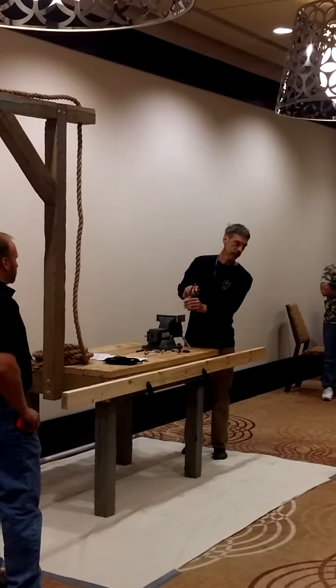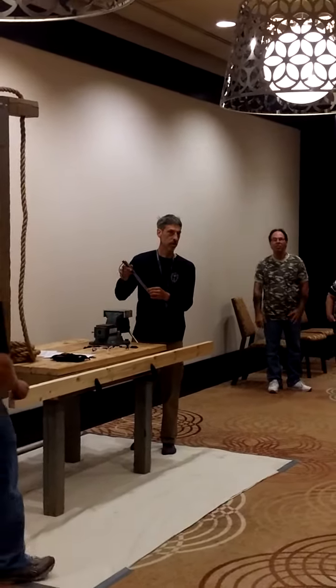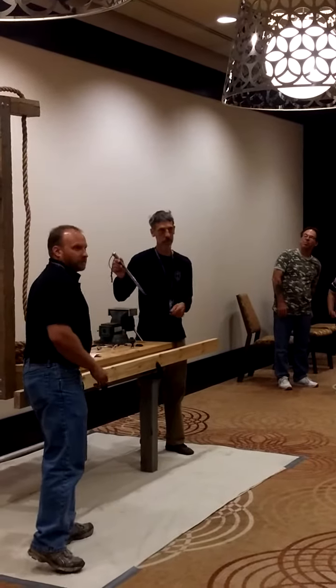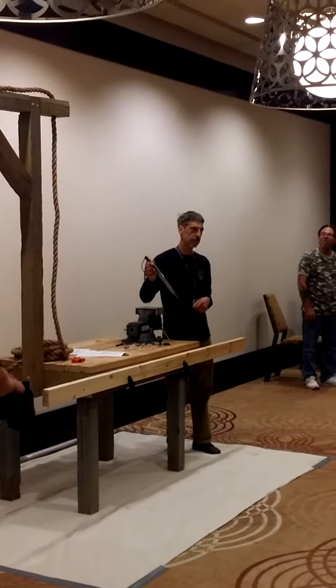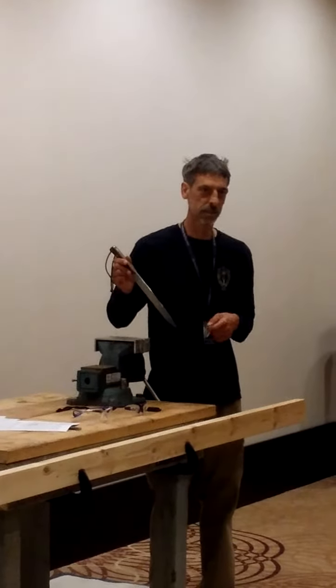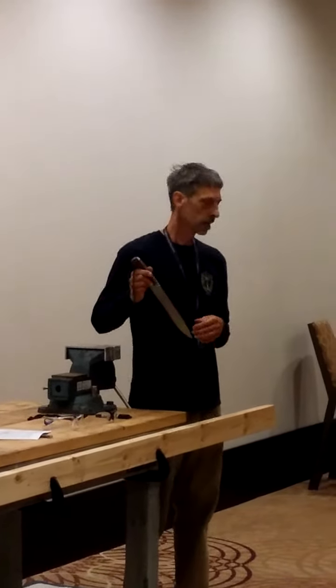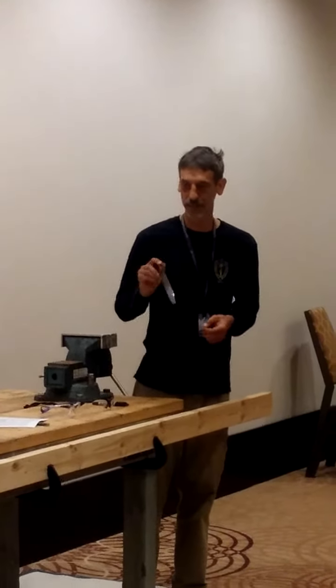And then it gets put into this vise here where it has to be able to bend 90 degrees without breaking. You can have cracking once in a while in front of the edge, but it's rare these days. In the 80s it used to be common that the edge would crack, but nowadays it's extremely rare. And often it comes back to almost straight, which is just incredible — the possibilities of what these knives can do.